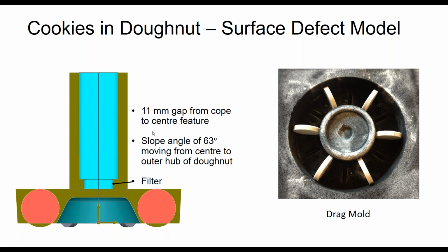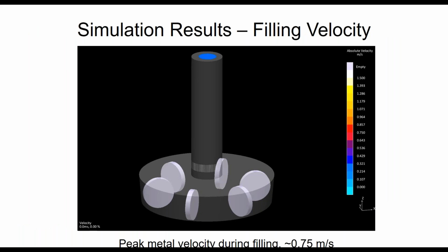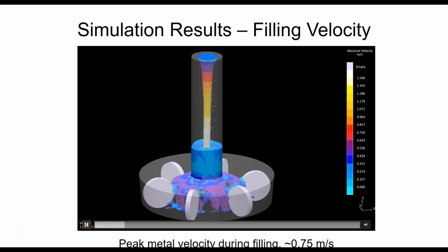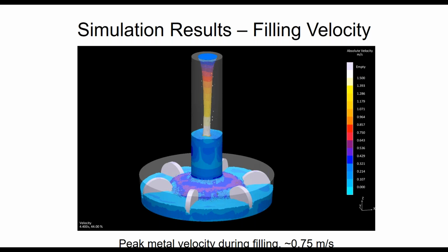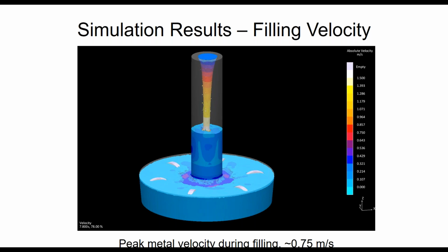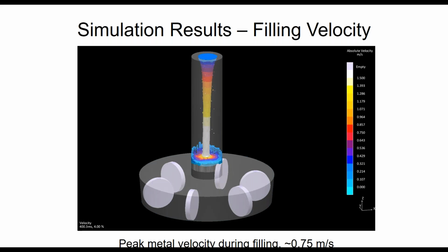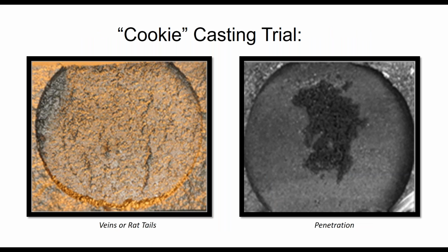On this next model, we call it the cookie and donut model because there are cookies that are shown in the drag half on the mold to the right, and we place that in symmetrical order on a core print where we wet these specimens again from a given head height at angles and through a filter that will allow quiescence. Recipes, different head pressures, etc., to understand what would cause certain concerns. And here are some of the classic concerns: the veins, the penetrations.